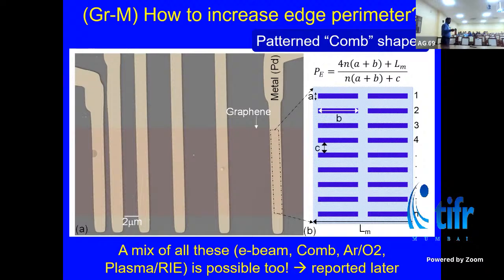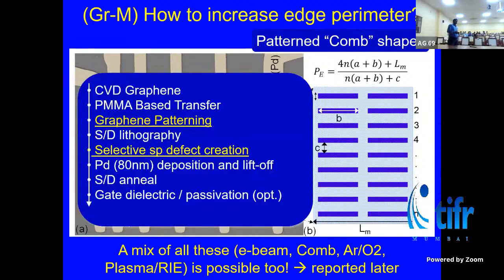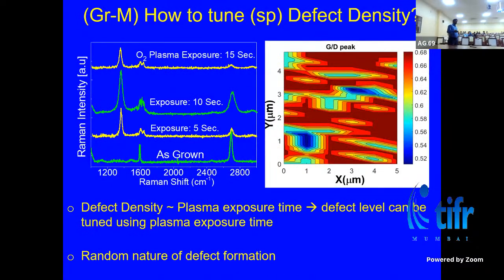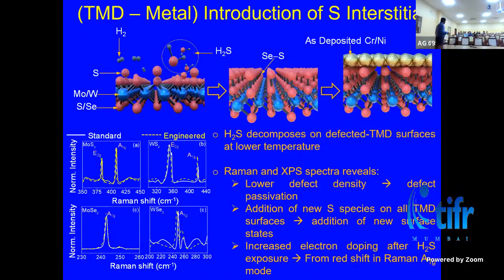It all looks clean because it went through a lot of technological optimizations in terms of growth, transfer, photoresist, residue-free patterning, cleaning, and a lot of other things that are also involved in this. That's why it looks great, all clean, looks single crystal. Right. So when you play with the plasma power, we figured out that you can actually play with the defect density, and then we use that further for engineering the contact, depositing metal on top.